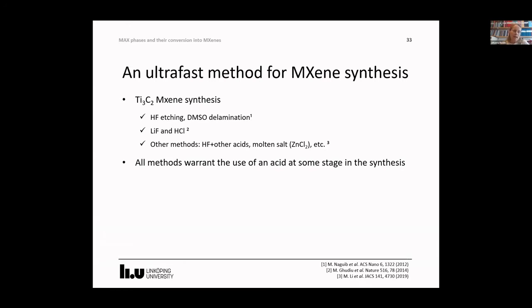So MXenes are, as you all know, typically synthesized by, quite often, time-consuming multi-step procedures involving a lot of chemicals. The first method was, as Michelle summarized in the introduction, HF etching. It was later followed by lithium fluoride and HCl, and more recently, other methods. But all the reported methods to date warrant the use of an acid at some stage in the synthesis process.